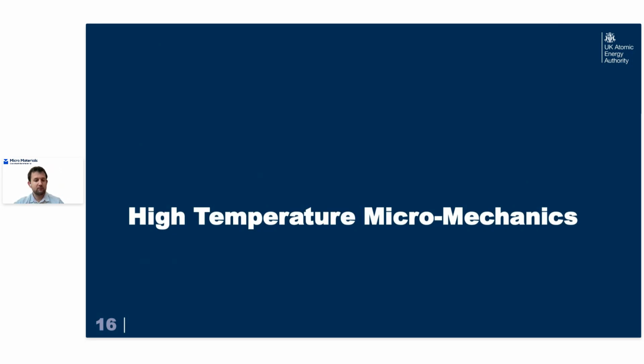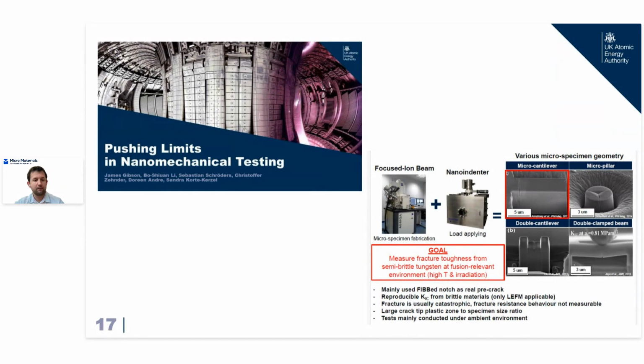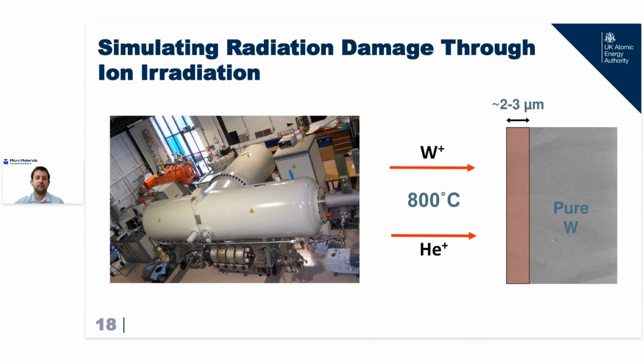So then if I move on, this is now micromechanical testing. This is all work that Bo did during his PhD. He was also looking at tungsten, these lovely plasma-facing tiles, but he wanted to understand their fracture properties. We're interested in tungsten, which unfortunately sits around the mechanical properties of glass when you look at its fracture toughness. So understanding that our fusion reactor will not shatter when we apply a load to it is obviously quite important to us. But we're limited, as we've seen, from having to use ion irradiated material, which limits us to trying to mechanically fracture test samples that will only be 2 or 3 microns deep in order to remain within that radiation damaged layer.